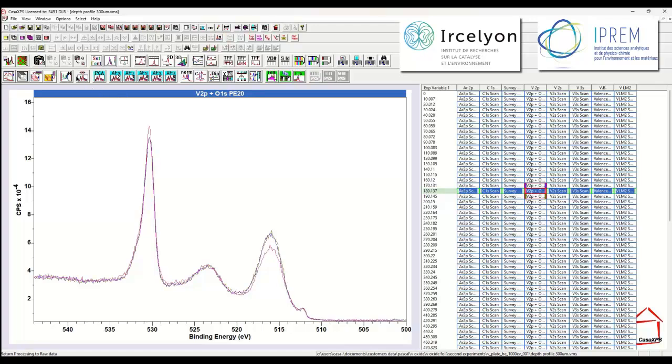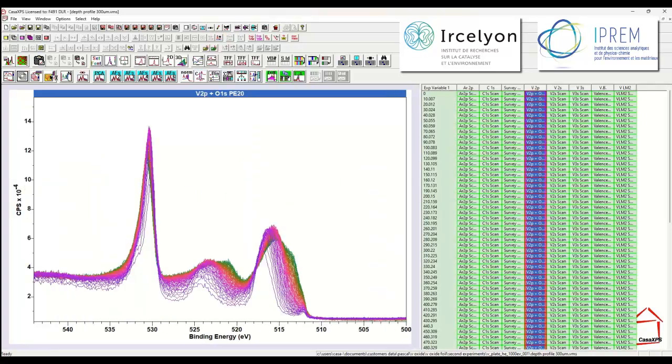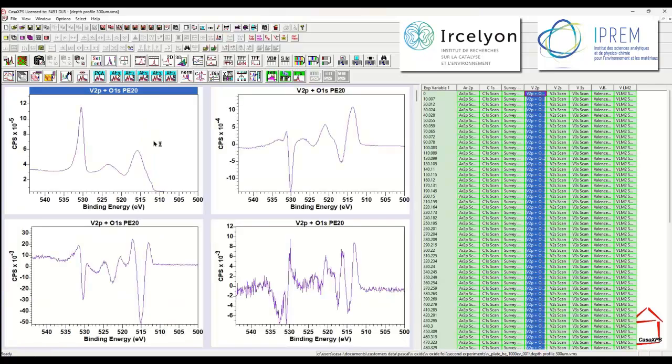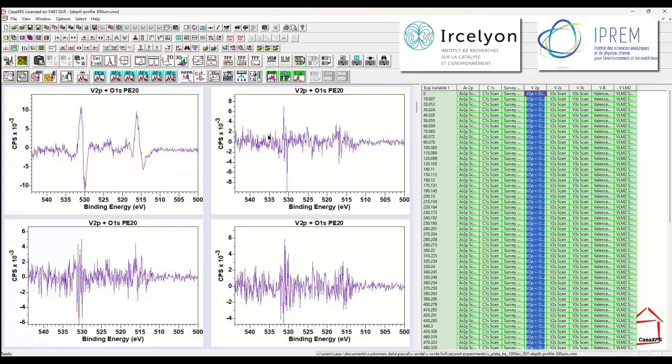So let me delete this line from the data file. And I'm going to the toolbar button that says delete VAMAS blocks. So the VAMAS blocks that I have selected I can remove from the file, and in doing so I should have a set of spectra without the anomalous signal. And when I do PCA again and look at the abstract factors, one, two, three, four, five, and now the sixth one looks like noise. So simply identifying the outlier in these data has managed to reduce the number of abstract factors by one. So my search has now been reduced from looking for six shapes to five shapes. And that's because there was something wrong with the data that I've now corrected in the sense that I've removed the spurious measurement.